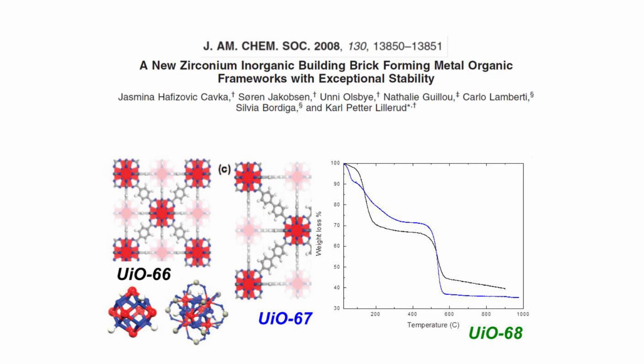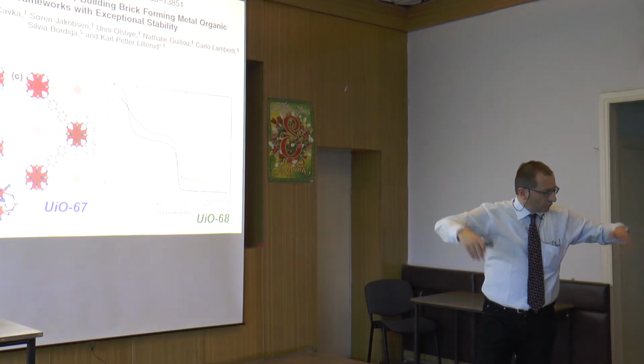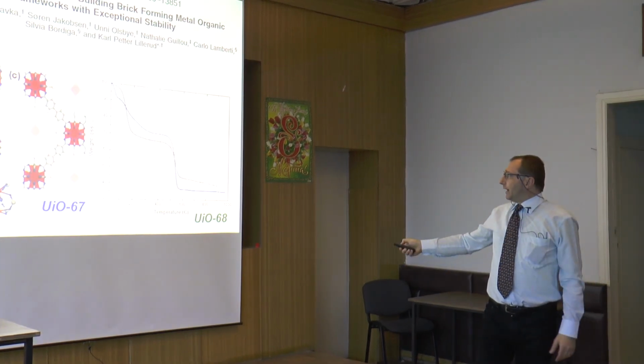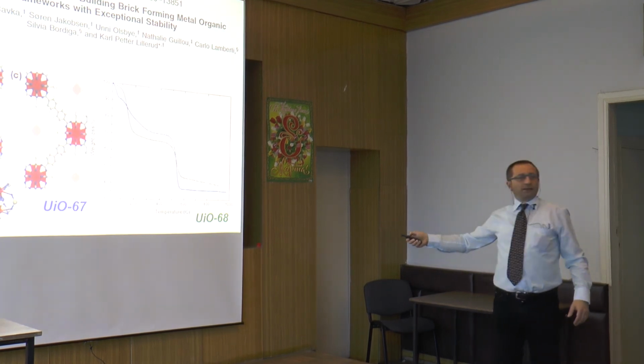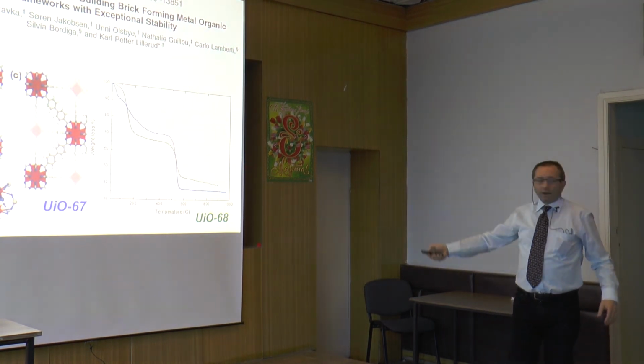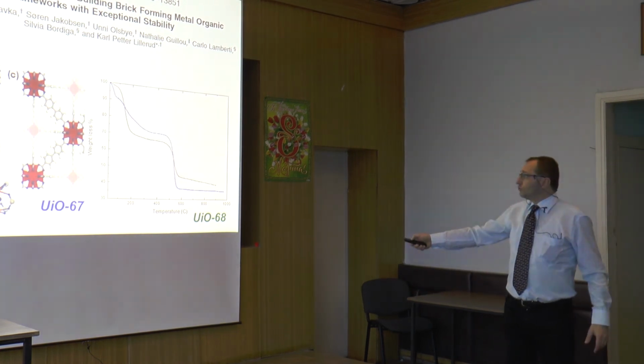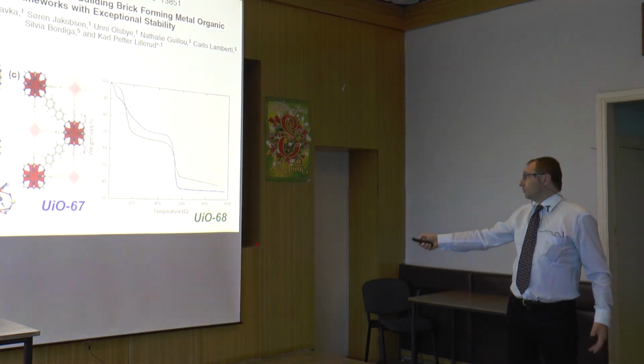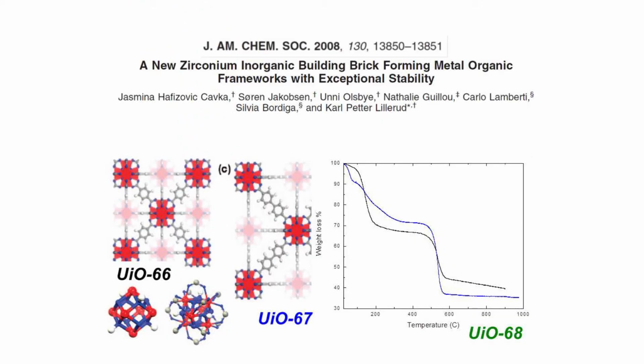One very important experiment is thermogravimetry. So basically you put your MOF on a balance, and you flux in oxygen and you heat. And what you see is a weight loss. So this first weight loss is the fact that, by heating, the solvent goes out. And this is very important. This is the stability plateau, the plateau where the MOF is stable. And these two MOFs are stable up to 550 more or less degrees.